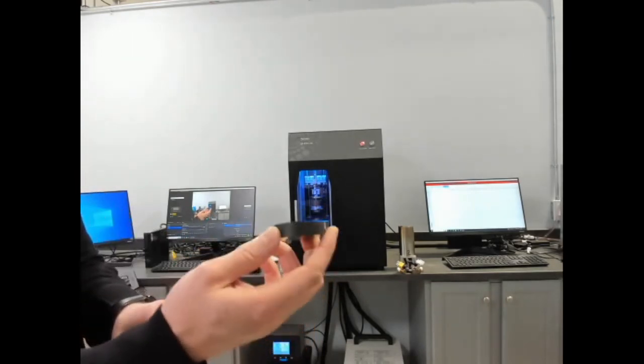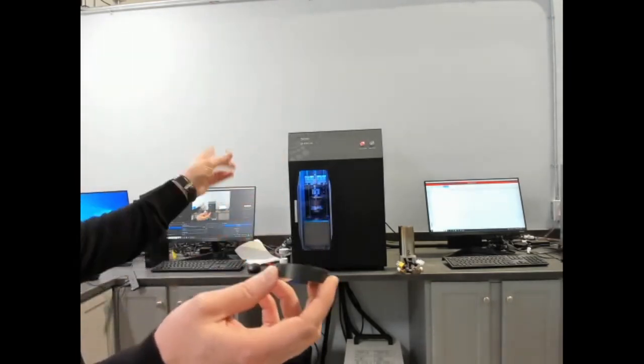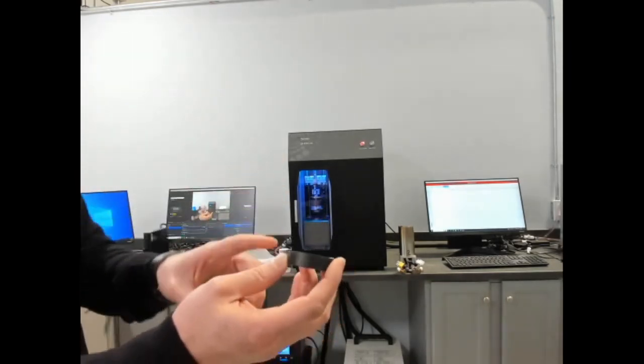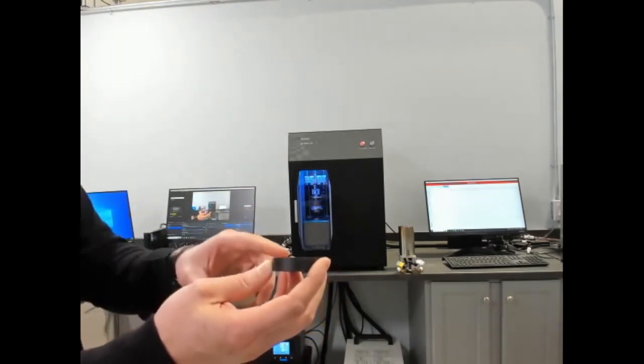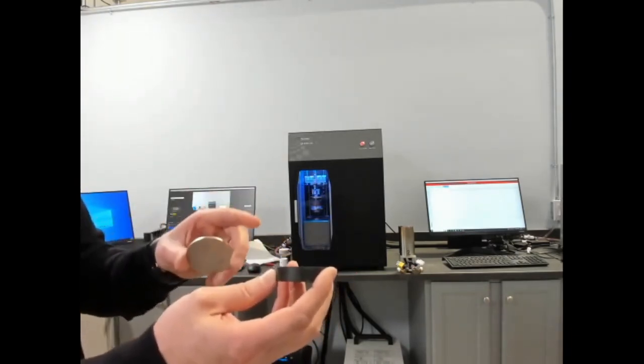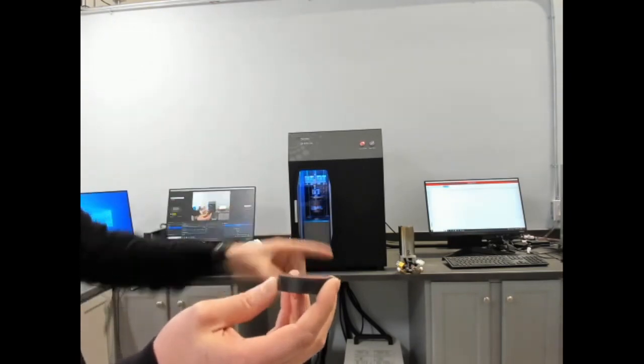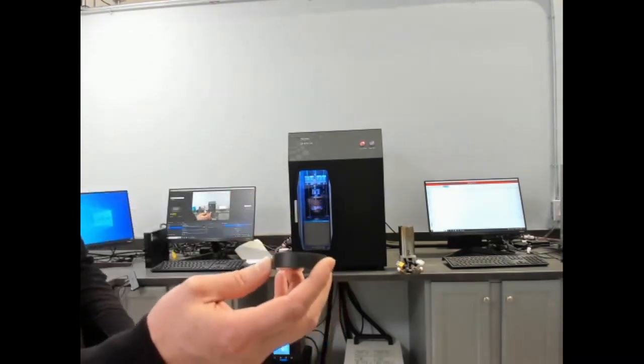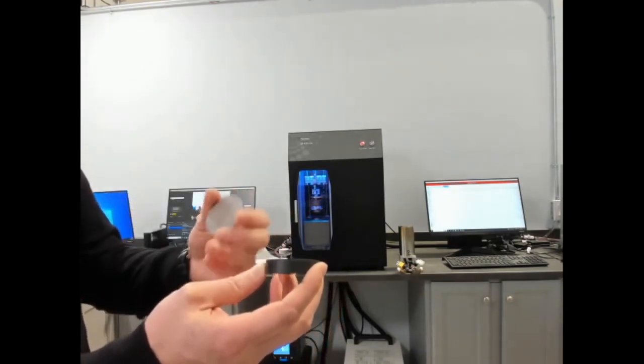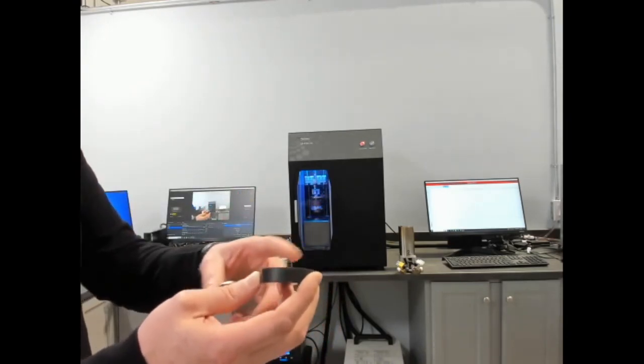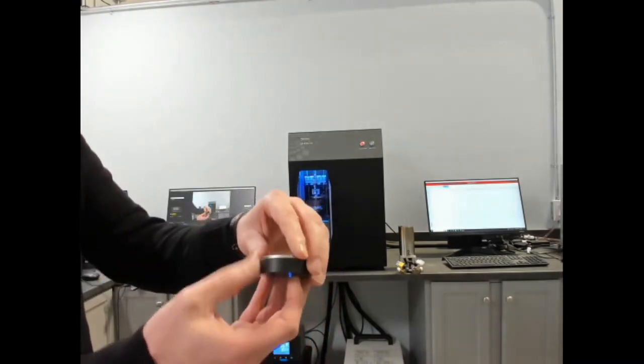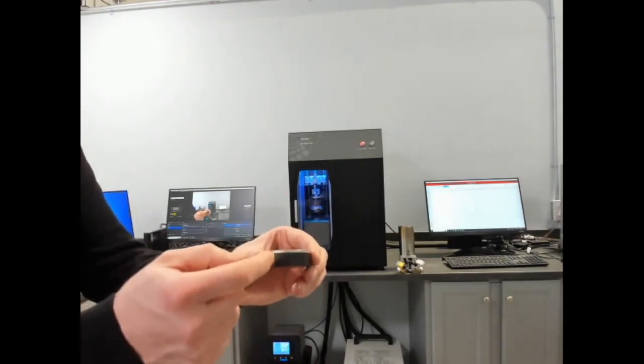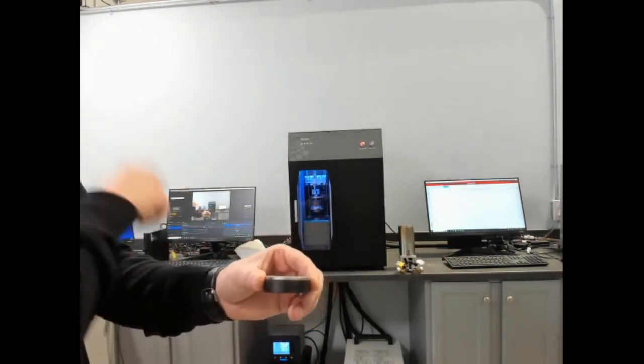And you can see on this sample that when you measure anisotropy and compare it to a steady state device, which measures the full thickness thermal resistance and thermal conductivity, the data is very good. The through thickness value matches the through thickness value from the guarded heat flow meter. And then you have the additional value of in-plane. And then we add this layer, and you can see the effect of it, that it's ever changing and it does not match. It never reaches the full value.